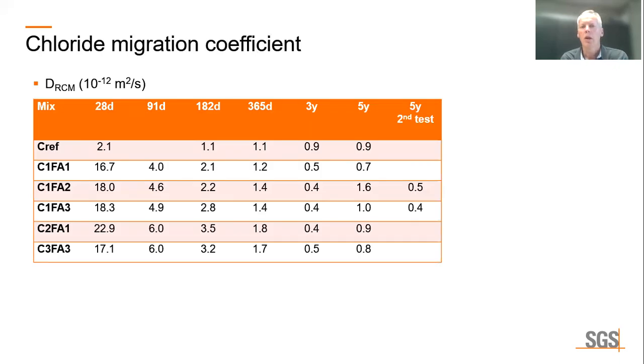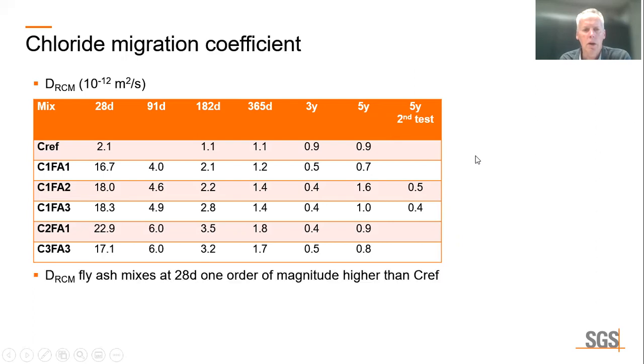Now let's take a look at the main results of the chloride migration coefficient, which is shown in this table for all testing times from 28 days up to 5 years.